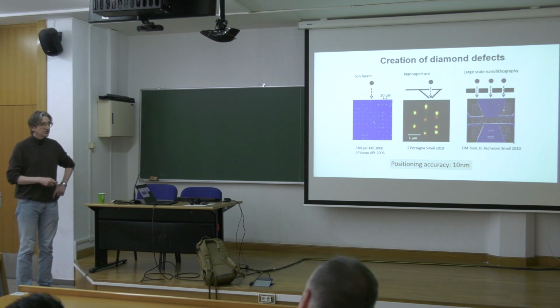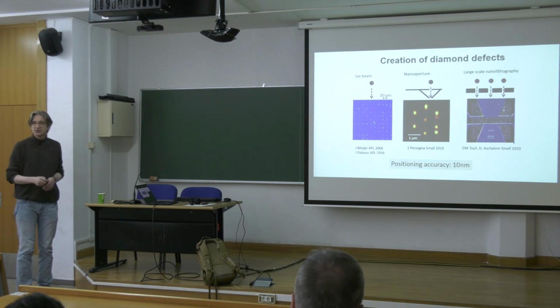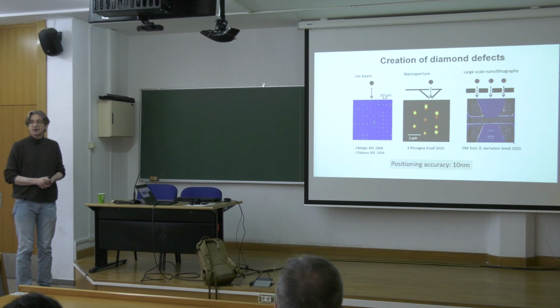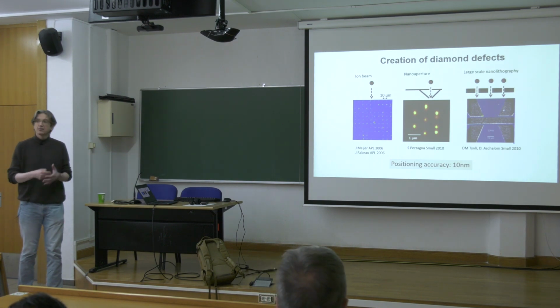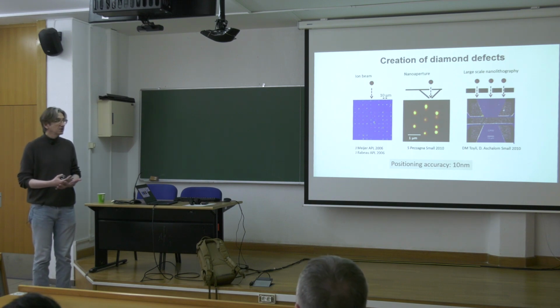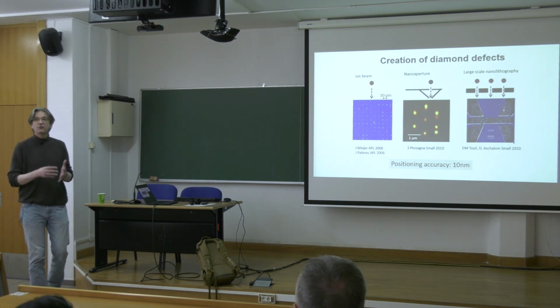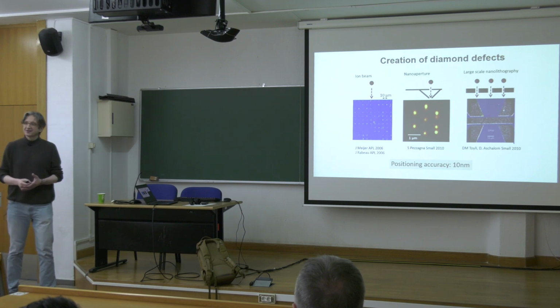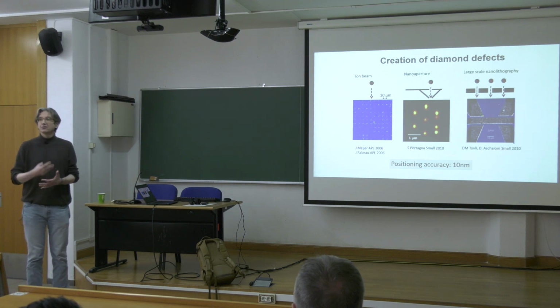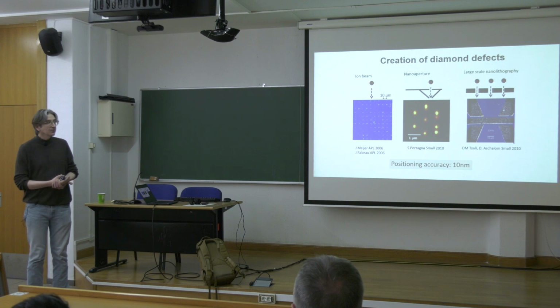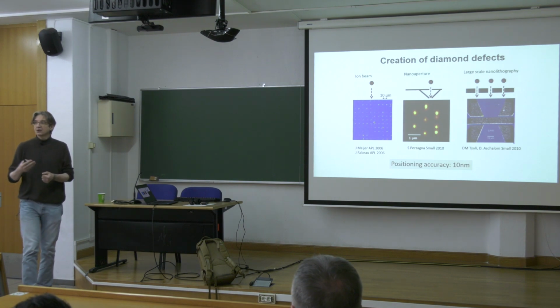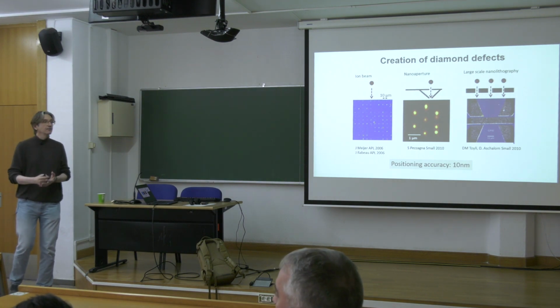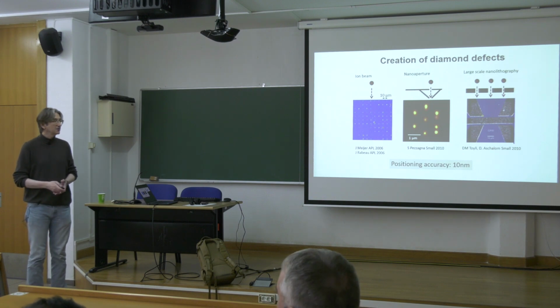In all these cases, position accuracy for these arrays or position of single NV centers is on the order of 10 nanometers. So you can place these qubits with a precision which is of molecular scale. And so this is interesting in terms of sensing, if you want to sense single molecules, or it can be interesting in terms of creating quantum computers, because at 10 nanometer distance, the interaction between two single electron spins is not negligible anymore. It can be stronger than any environmentally induced decoherence in the system.